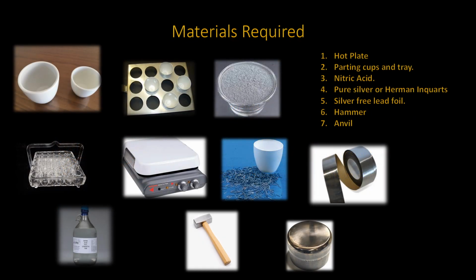To start, a hot plate of some type will be needed. It is used to speed up the reaction of the nitric acid. Ceramic or glass parting cups, having a capacity of 10 to 12 milliliters, are necessary. The nitric acid solution should be of a high concentration. It will be cheaper in the long run when you dilute it to what is required. The silver is used for inquartation if required. It must be lead-free. For the inquartation process, silver-free lead foil will be needed, or Herman inquarts may be used. A hammer and an anvil will also be required. The anvil and hammers that are used for this process are designed to be contaminant-free.